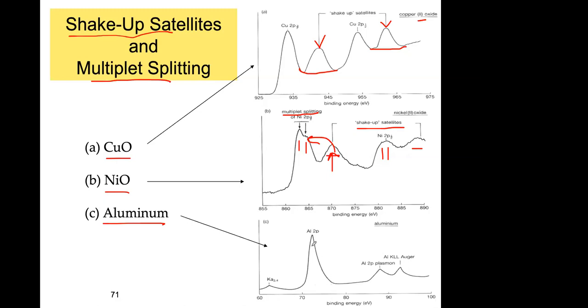And this is the 2p signal, which should have two peaks, but you see only one. There is a shoulder here. But then you have this plasmon. This is like a shake-up, but it's a plasmon. It's that you are exciting the electron cloud on the aluminum, that's basically in the conduction band. Those electron clouds can be excited. So these are 2p electrons, but they lost this energy because that energy was used to excite the plasmons on the aluminum.